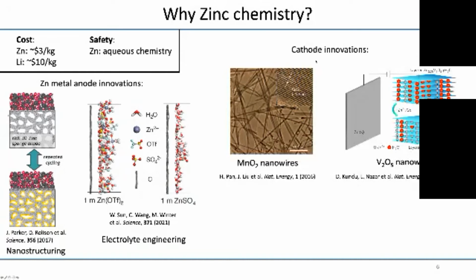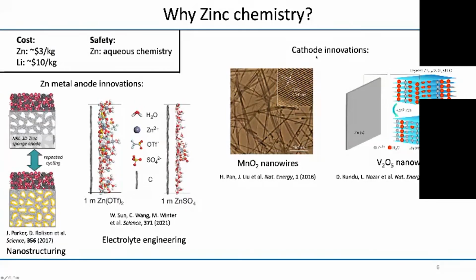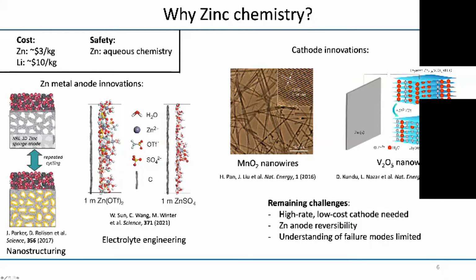And on the cathode side, there have been demonstrations of transition metal oxide nanostructures that allow for higher capacity, a higher amount of zinc being stored. But it's unclear right now what these mechanisms for storage are on the cathode side, which leads me to the remaining challenges that we hope to address in our proposed work. We want to develop a high rate but low cost cathode material that can store zinc at high capacity. And we want to enable the zinc anode to be reversibly operated without dendrites or loss of efficiency.